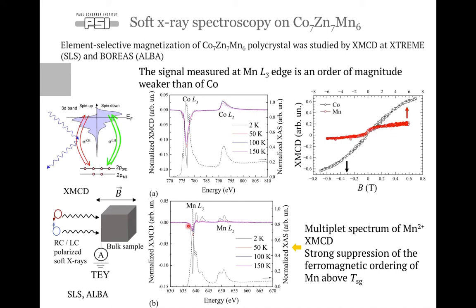But for manganese, the XMCD signal is really, really tiny. What is interesting, the XMCD measured as a function of magnetic field cannot be saturated even by the high field of 6 Teslas. So that suggests some antiferromagnetic frustration in the manganese sublattice.